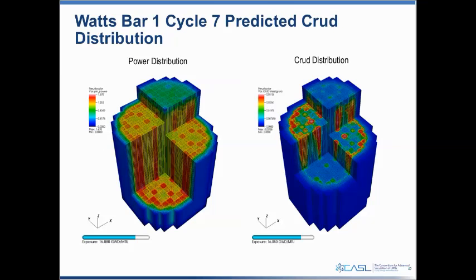We did simulations then with the three coupled codes that Brian and Kevin had talked about: the impact transport neutronics, the CTF subchannel thermal hydraulics, and the Mamba crud and chemistry code. The left figure is just a predicted power distribution, right before that turbine blade shutdown. Prior to that, you can see the power distribution on the left side. The red is the hottest assemblies, typically the fresh assemblies. If you look to the right, you'll see the corresponding crud deposition occurs in those higher powered assemblies. Those are the ones that are going to have subcooled boiling, typically only in the upper half of the core, and that's where you see the crud distribution in that right figure.